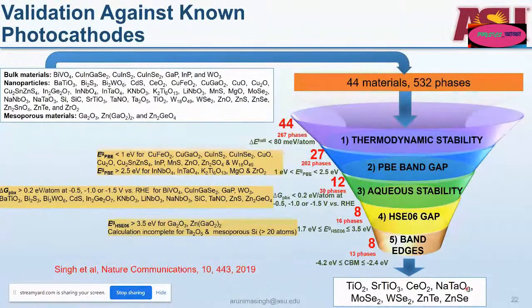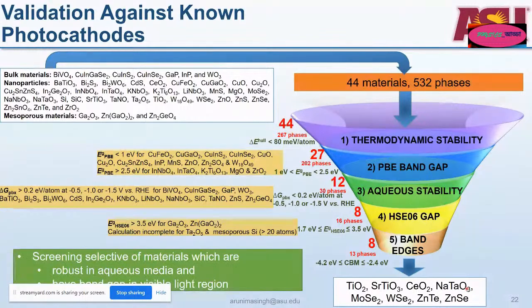We see the most widely studied CO2 reduction materials emerge out of the screen: TiO2, ceria, MoSe2, WSe2. What it tells us is that the materials which come out of this screening are highly robust in aqueous media and have a band gap in the visible light range. And the screening is highly selective of materials which can satisfy these two things. So that means, if anything, our screening was very selective and was able to get candidates which are going to be extremely robust in aqueous media and have the promise of absorbing a good fraction of the solar spectrum.